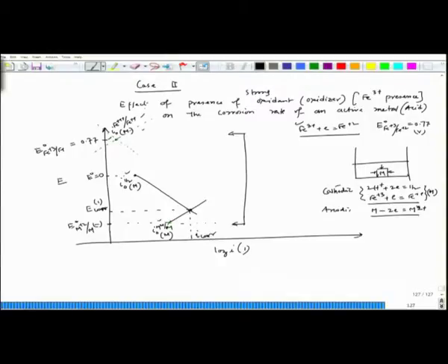Now, once we have the presence of Fe+3, it is a strong oxidant. That means it will have a very high tendency to get reduced, and there would be strong cathodic polarization because it is a very strong cathodic reaction. And remember, all these individual redox reactions or half cell reactions would have their own anodic as well as cathodic polarization. So this is anodic polarization for hydrogen evolution, this is cathodic polarization for metal, and this is the cathodic as well as anodic polarization for Fe+3 to Fe+2.